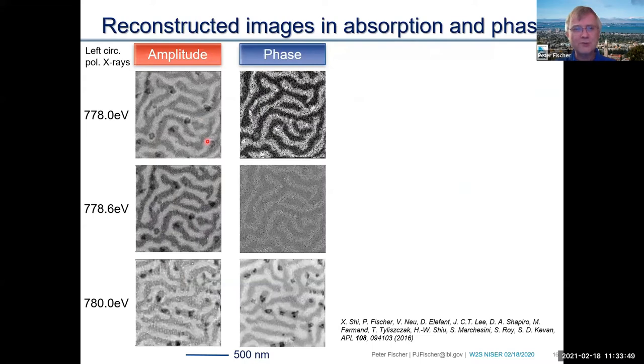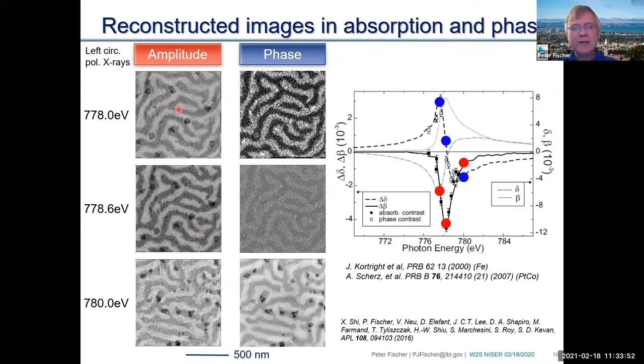Now, what is interesting here, just to share a little bit of detail: the amplitude contrast, of course, when you vary the energy across this cobalt edge, as I showed you earlier, follows more or less the contrast. That means the stronger the contrast, the stronger the XMCD signal is here. And as you can imagine, at the resonant edge, this was 778.6 eV, for those of you who paid close attention, this is where the contrast is strongest, and it's a little less before and after. Now, when you look at the phase, and of course, amplitude and phase are related by a so-called Kramers-Kronig relationship, you see a different behavior. This is also drawn here by the red dots and the blue dots. The blue is the phase, and the red is the amplitude. There, at this resonant edge, you see almost no contrast, while there is a strong contrast just slightly before the edge, and then a reverse contrast after the edge.